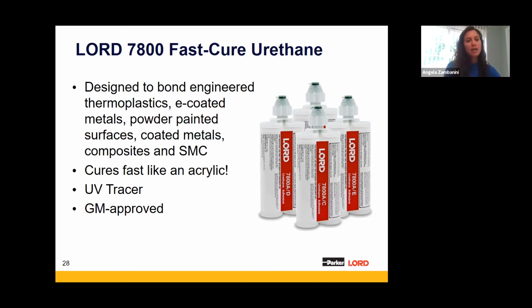The other thing that we added with this urethane is a UV tracer in case you're using dark panels or putting it into boxes and it's difficult to see if you've properly sealed everything. So we put a UV tracer in there to help automate if you want to use a robot, or if you want to just go in there by hand and use a black light. The other difference with this adhesive is it's GM spec approved as well. So it went through that GM automotive spec for bonding plastics, which really just shows the level of environmental resistance that our adhesives get.